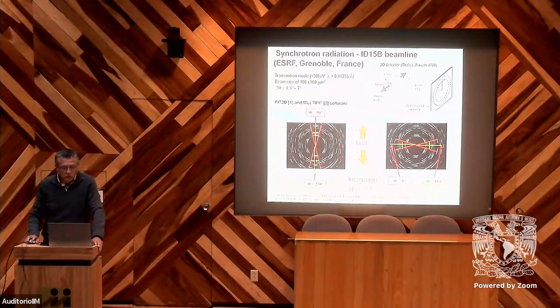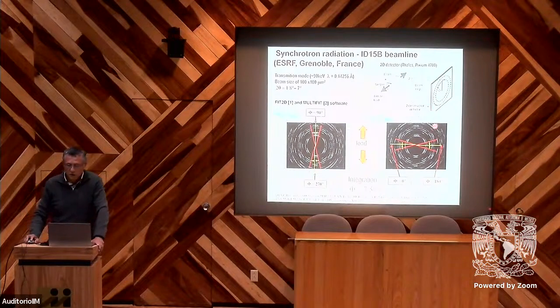And for this, we use the source of ESRF in Grenoble in France, and we use very high energy and relatively small beam size, and with high energy we have very low angle diffraction. But this will be compensated by the use of a 2D detector, meaning we can have information in many directions, and also a very large distance between our specimen and the detector.